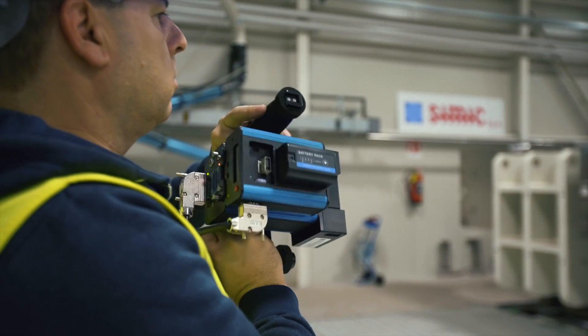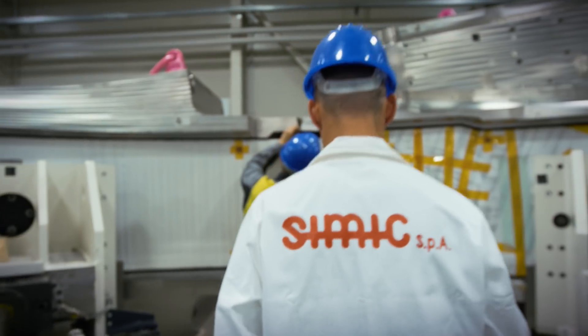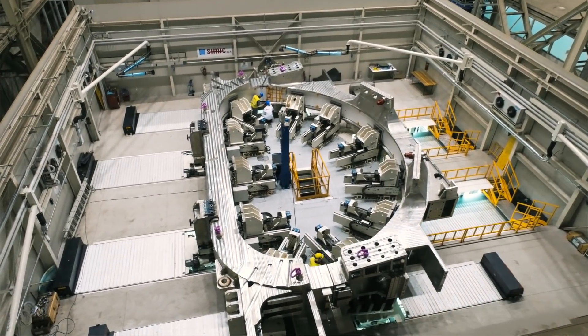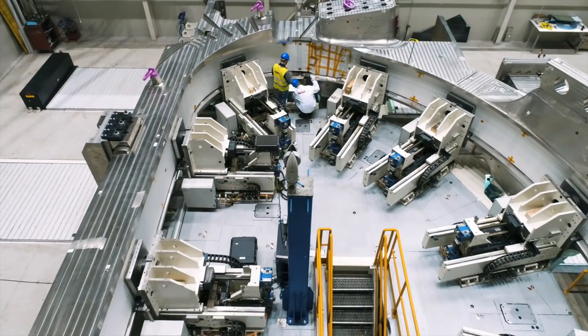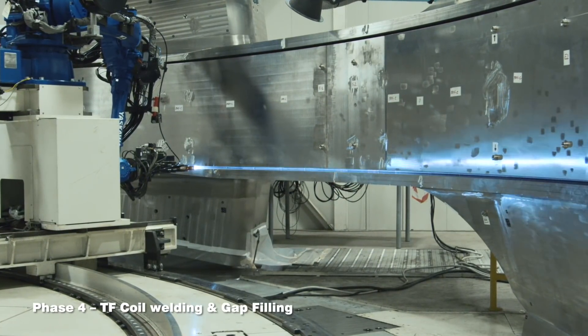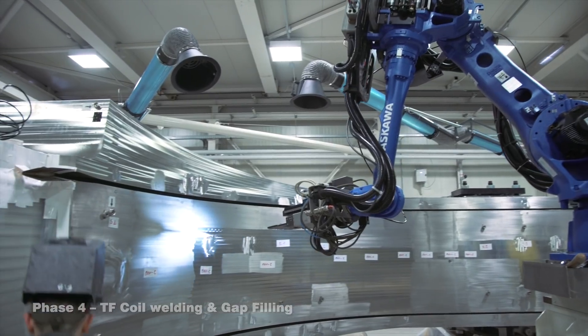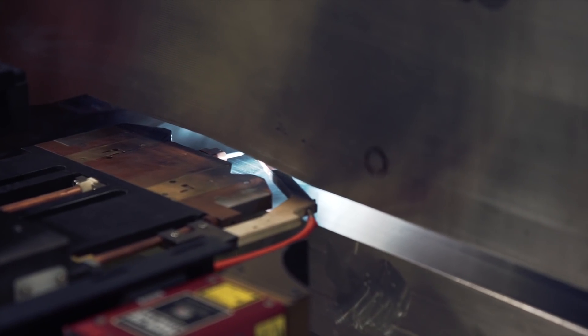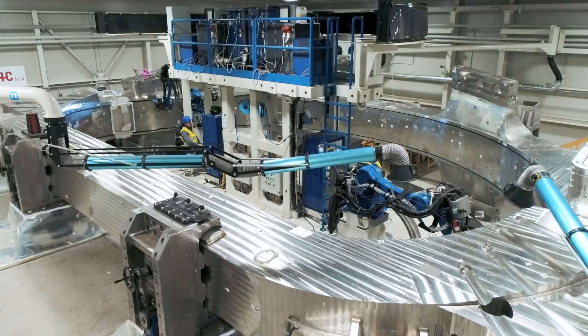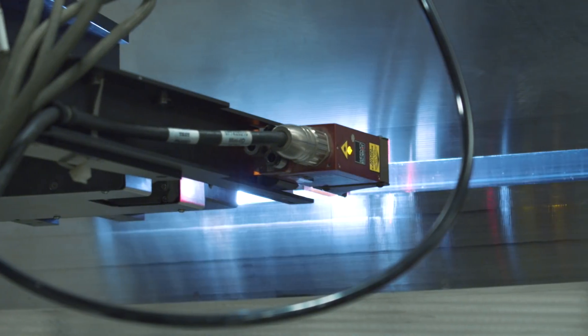Experts constantly monitor the positions, forces, and torques on each component to guarantee a perfect fitting between the coil cases and the winding pack. The assembly rig is the key machine for the TF coils. A combination of manual and robotized hot wire narrow gap TIG technologies are carried out to complete over 80 meters of welding with a thickness of up to 125 mm, with welding processes qualified at 4K, and inspected by sophisticated UT phased array pushed to the limits of the technology. Welding deformations are constantly monitored by laser tracker and photogrammetry.